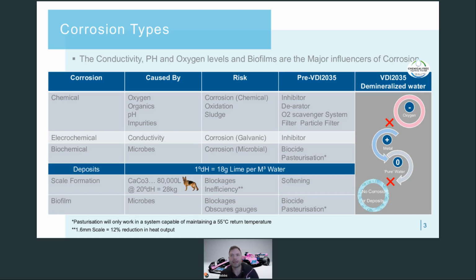Traditionally, degassing, oxygen scavenging through inhibitors or sacrificial anodes is used, but a correctly specified, filled and maintained system should prevent oxygen ingress. Removal of oxygen, as you can see in pink in this diagram, is the first step to break the corrosion chain. Secondly, electrochemical corrosion is caused by conductivity, especially a problem where dissimilar metals are present and where there are minerals in the water. This is usually addressed with chemical inhibitors, but instead, simply demineralizing the water eliminates the conductivity. If you remember those dissolved minerals with differing electrical charges from the last slide, they're gone, and so the corrosion is stopped.